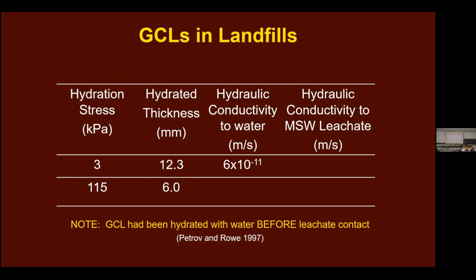Now, let's look at the effect of both stress and permeate. So we're going to take a GCL here. We're going to hydrate it with clean water. And we're going to do it at 3 kilopascals and at 115 kilopascals. 3 is a simulation of the bottom of a pond with, say, 0.5 meter of cover soil, or it's a pretty good approximation for below a wrinkle in a composite liner. 115 is a quite low effective stress for many applications. And you can see the thickness changes by a factor of 2. Go from 3 to 115 because it consolidates.